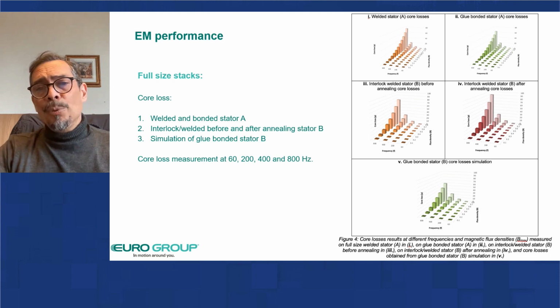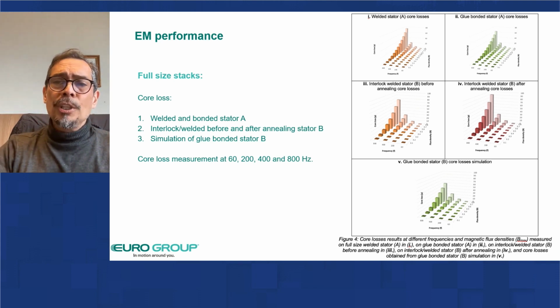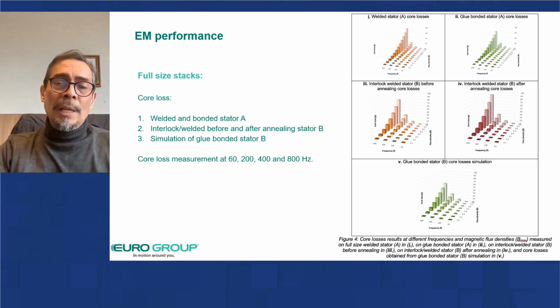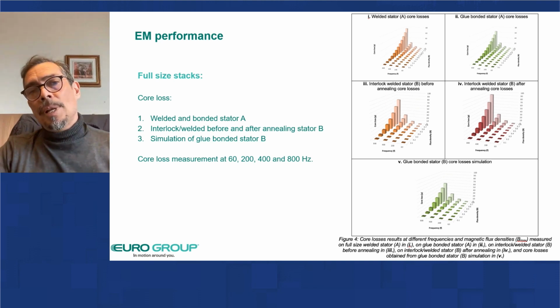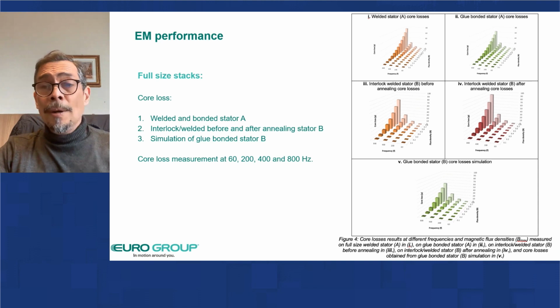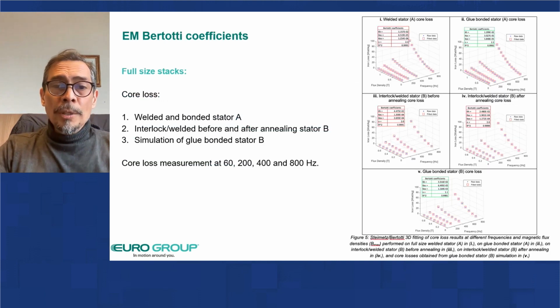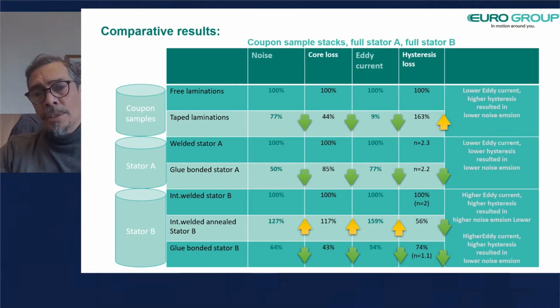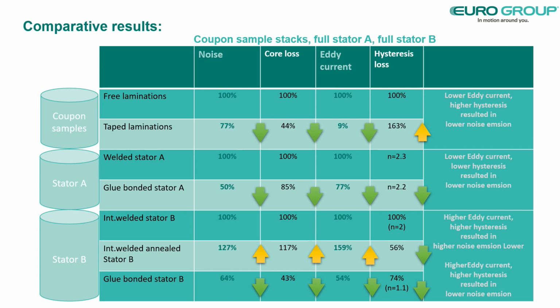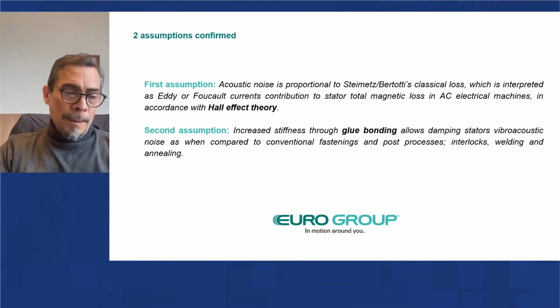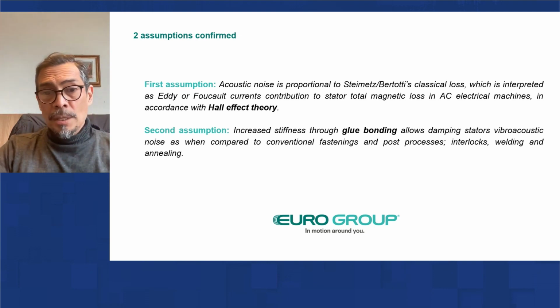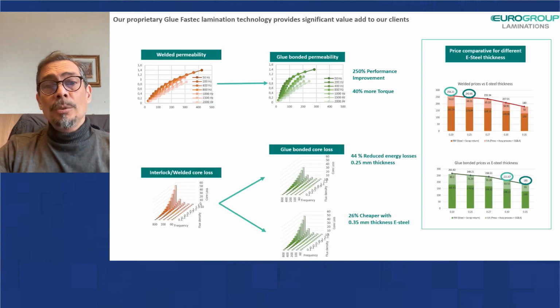We are capable of relating this vibroacoustic behavior with the welding, and also with the annealing that will damage the lamination, since the welding already damaged the lamination and the special alloys that I mentioned before. So what we're saying in these articles is it is beneficial to go glue bonding, and we presented a rationale where glue bonding allowed to reduce eddy currents, and I'm going to jump fast on these because eddy currents were shown to produce the vibration that I mentioned before. But because I see that I only have a couple of minutes remaining, I'm going to jump to the last study that I wanted to show you.